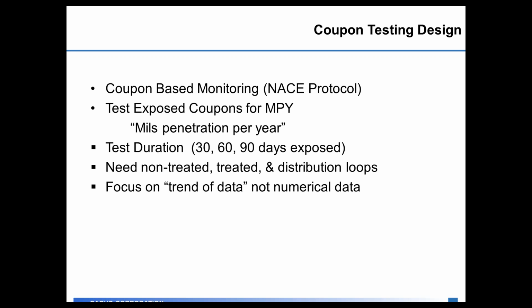Typically what you're going to look at is a test duration of 30, 60, or 90 days, with 90 days being most common, because in the first 30 days these new pieces of metal corrode faster than they would over the long term, and so your numbers have much more bounce in the shorter coupon tests.